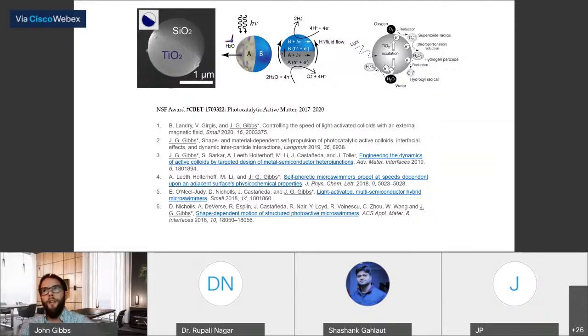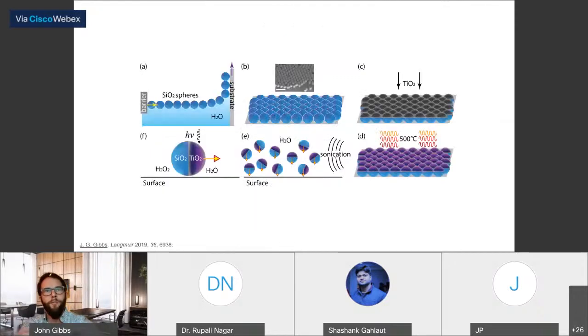One of the nice things about this project is that, as you probably know, there is a huge amount of research being done on photocatalytic materials, for converting sunlight into energy and so forth. We've taken some of those ideas and determined that we can utilize some of the same processes to gain better control over the way these particles not only self-propel, but also interact and self-assemble with each other. This is a really simple process to fabricate this particular particle, the Janus sphere. We take the silicon dioxide particles and functionalize them so that they become hydrophobic. So they'll actually sit right on top of water.